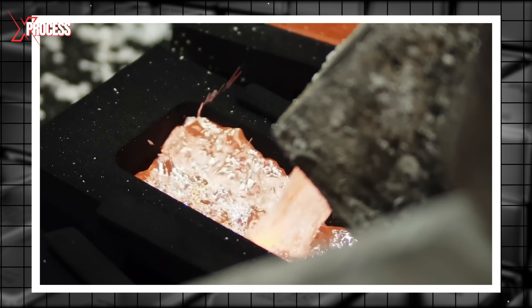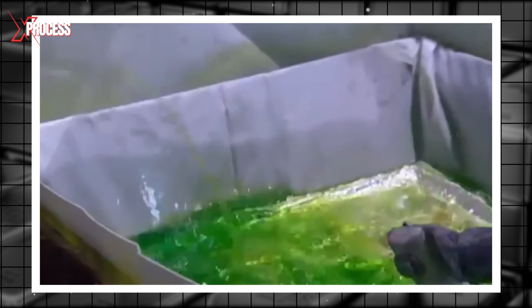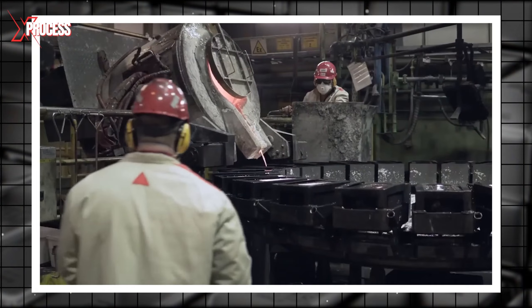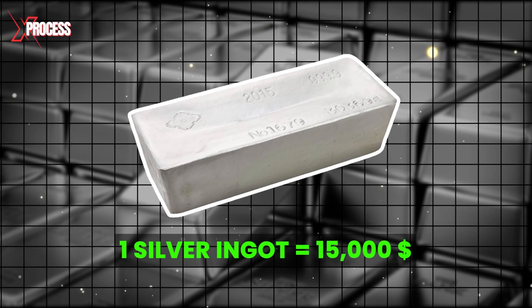The remaining 1% is revealed as gold. Separating these two precious metals is a precise process accomplished through electricity. Plates submerged strategically in a silver nitrate solution play the leading roles. As electricity is applied to the solution, the silver dissolves and re-emerges as a new negatively charged plate, leaving the gold behind on the positively charged plate. This process allows for the extraction of 99.9% pure silver, ready to be transformed into shiny ingots, each with a value of approximately $15,000.